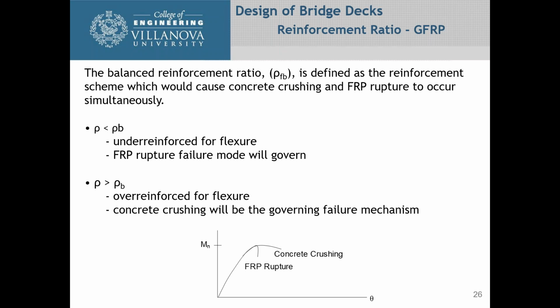For GFRP, we have to design it the opposite, because remember we said that the failure of the GFRP bars was a brittle failure. So if we load this and we get to the yield point of the GFRP, you're going to have a sudden failure. So you want to over-reinforce it so that when you get close to failure, the concrete is the indicator of overstress, so that you don't get a sudden failure. You start seeing the concrete crack and crush, then you know that you have an issue before the GFRP bars fail.